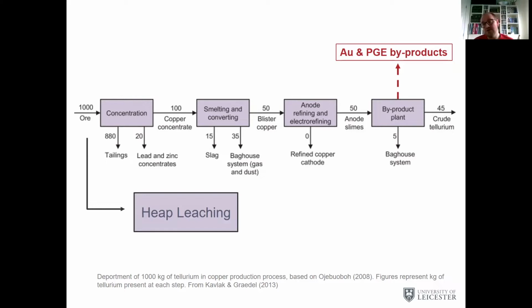There is an alternative way of processing copper, though, and that is to not bother separating it after you've crushed it, and to not bother sending it to a smelter, and then to not bother sending that blister copper to a refinery. An alternative method, which is more relevant for highly oxidized ores or for very low-grade ores that many of our porphyry deposits are now facing, is to heap leach them.